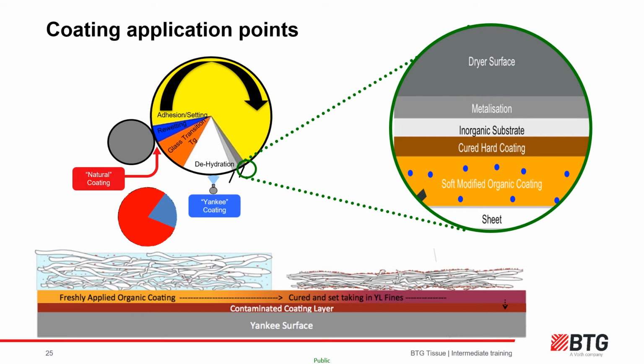If we imagine the contamination levels increasing in the backwater, then more contamination will be taken into the coating and migrate into the cured coating layer. This layer will then grow. On machine we see it as the coating layer becoming more opaque or heavier. Blade vibration usually increases, and we usually hear it too as an auditory change. If this layer grows too big, then it moves closer to the blade, which can sometimes be controlled by running very high levels of release.